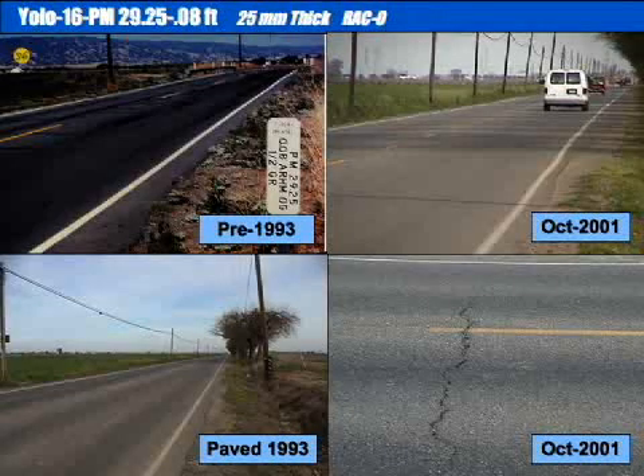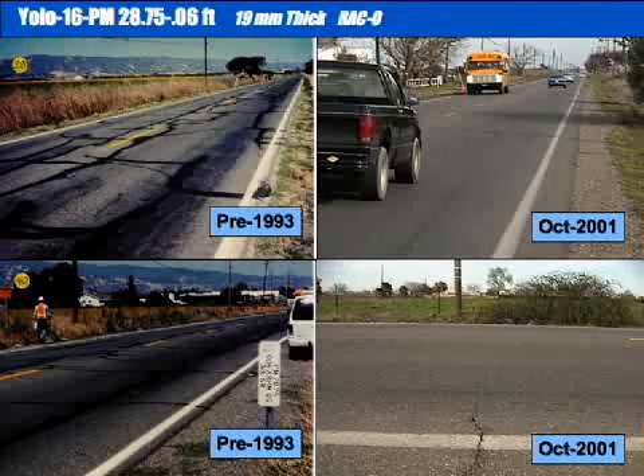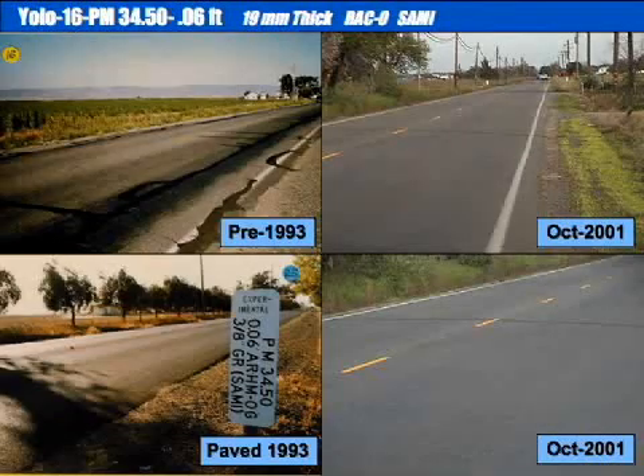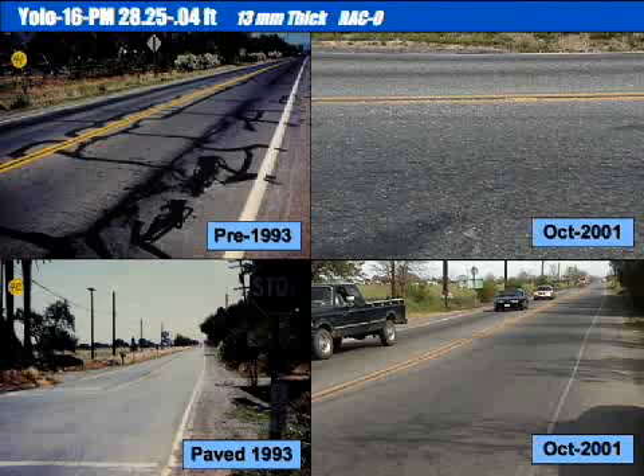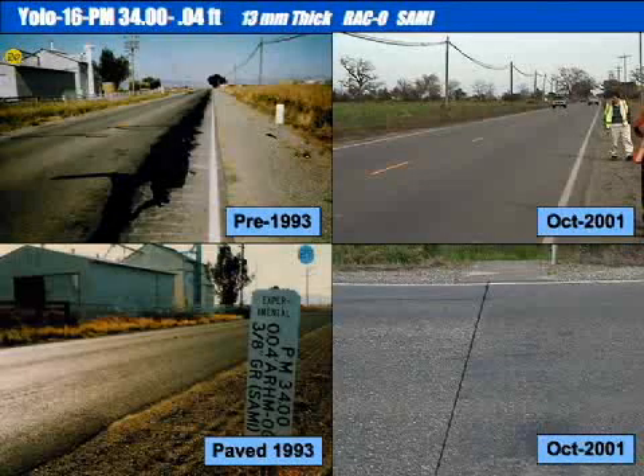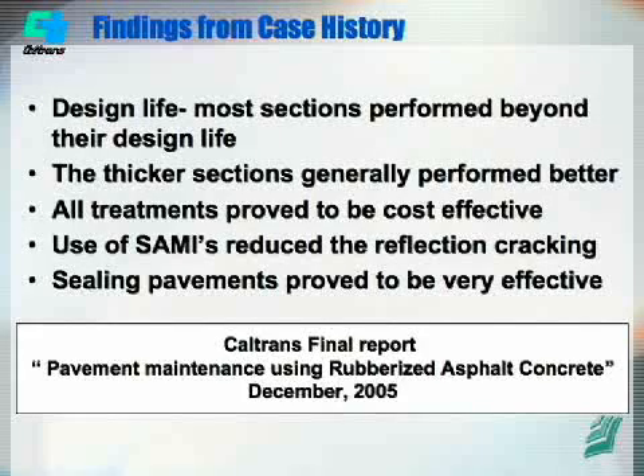And then we have the open graded 25 millimeters, which showed excellent performance. Also 19 millimeter thick open graded, and also open graded with a SAMI, 19 millimeters. We also went even thinner, 13 millimeter, another one with SAMI and without SAMI.